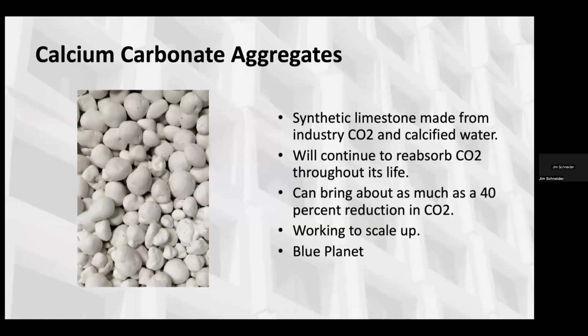There's also this article in a publication called Interesting Engineering that talked about a study that was done at Washington State University, where traditionally, I think you'd see biochar used at about 5% in a mix. They were able to do some kind of process with the biochar where they washed it with some of the concrete wastewater, and they got it up to like 30%. And that really sucked up about 23% of its weight in carbon dioxide from the air, while still achieving a strength comparable to ordinary cement. So there's some interesting study going on in that area that could be a possibility, again, as a sort of replacement for some percentage of cement.